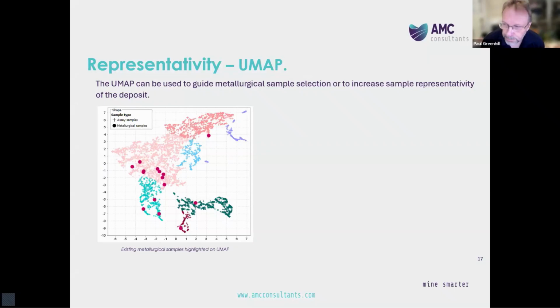So here's a further example where we've used the UMAP to identify geometallurgical groupings in the deposit that have really only been sparsely sampled for metallurgical testing, if at all. So in this instance, we can see that there are 7 geometallurgical groupings represented by the different colours, and you can see the metallurgical samples plotted in large red maroon circles, or red pink circles.